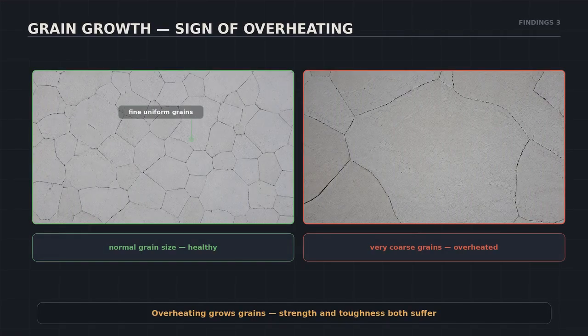Grain growth is even more direct. These 3 fields are the same magnification, count the grains. Fine and healthy on the left, larger in the middle, a warning, and very coarse on the right. When grains grow 5 or 10 times, the steel has been overheated. Strength drops. Toughness drops.